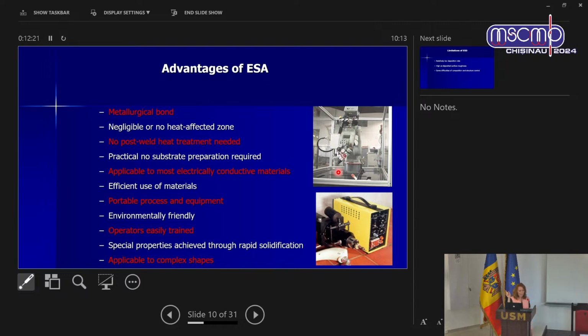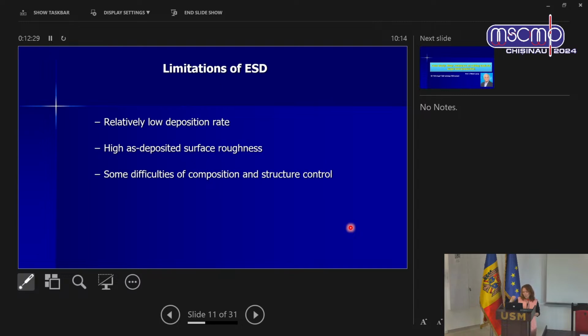And that's why the limitations of this method are a relatively low deposition rate when we are speaking about manual deposition, also high as-deposited surface roughness, and some difficulties of composition and structure control, because when you are doing it manually, it can be tricky sometimes.